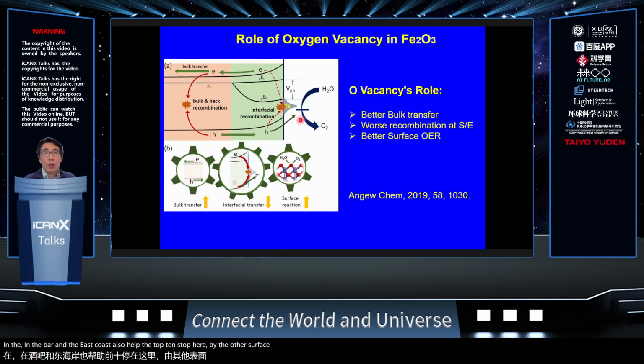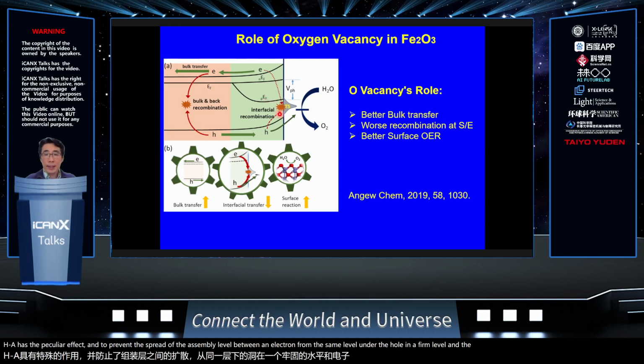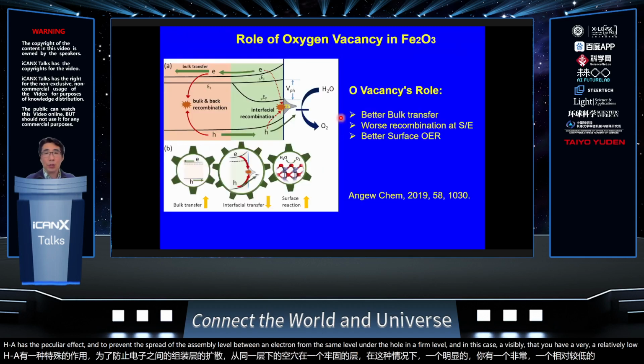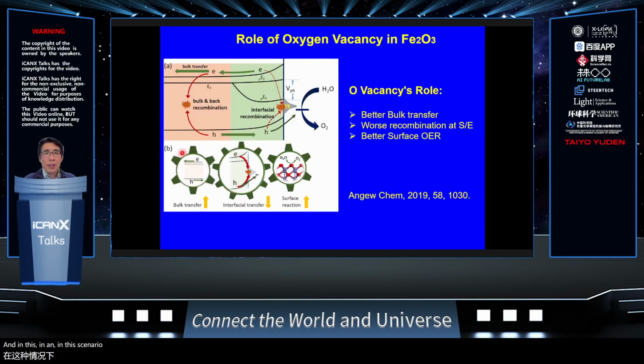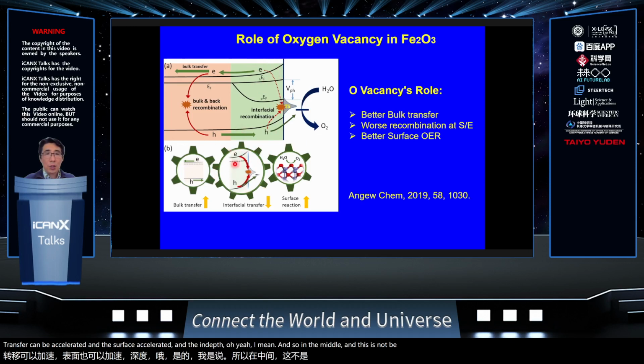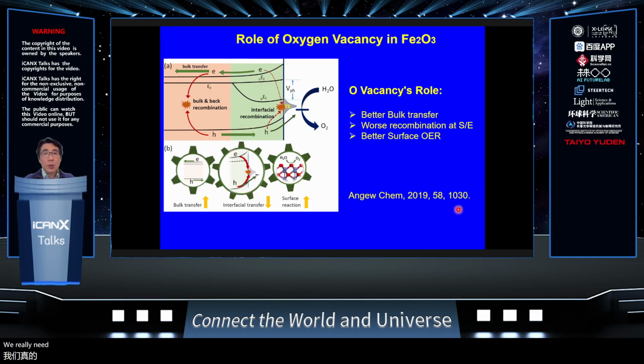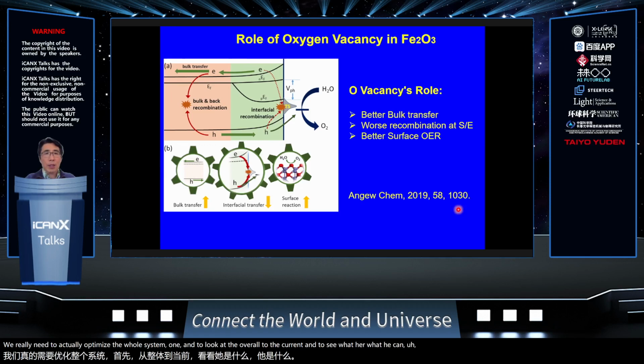But on the surface, because of the introduction of oxygen vacancy, it basically behaves like a trap state with a pinning effect, which prevents the splitting of the Fermi level between the electron quasi-Fermi level and the hole Fermi level. In this case, you have a relatively low VOC. In this scenario, the bulk transfer can be accelerated, the surface accelerated, but the middle and the interface are not good. The oxygen vacancy is not good for the whole system. We really need to optimize the whole system and look at the overall photocurrent to see how it can improve the efficiency.